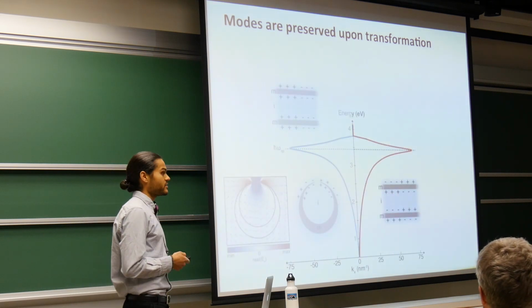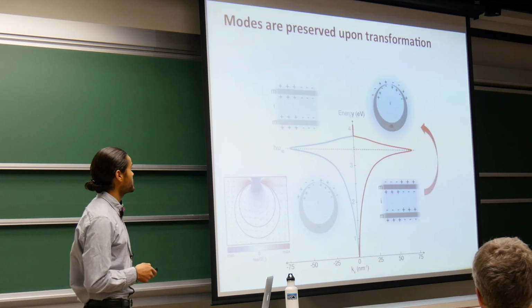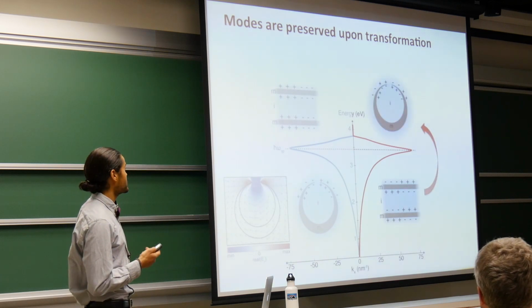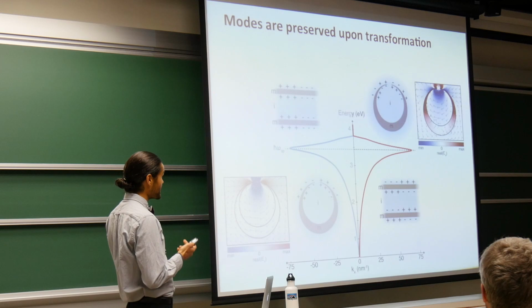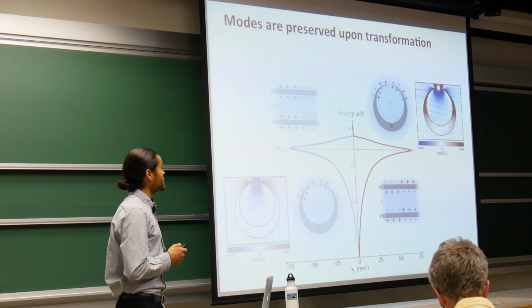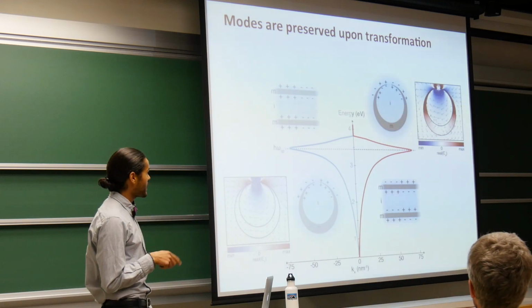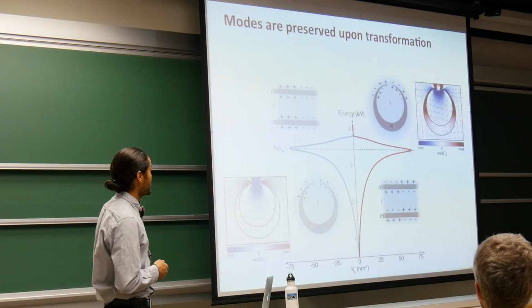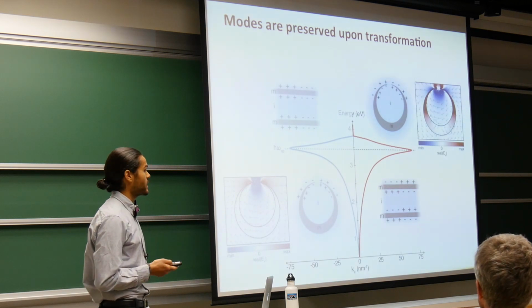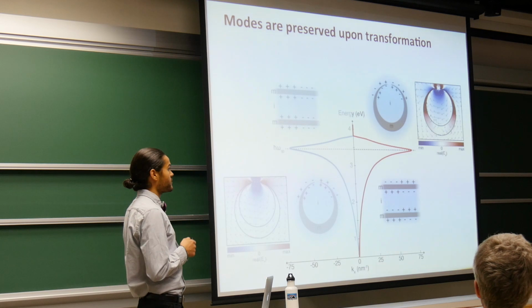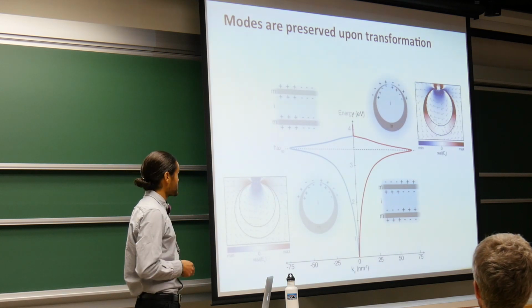If we look at the positive index mode with the antisymmetric charge distribution, again, this charge distribution is preserved upon transformation. And when we look at the near-field plots, we actually see counter-rotating displacement fields indicating a very small net magnetic moment and higher spatial variation of the fields at the tips.